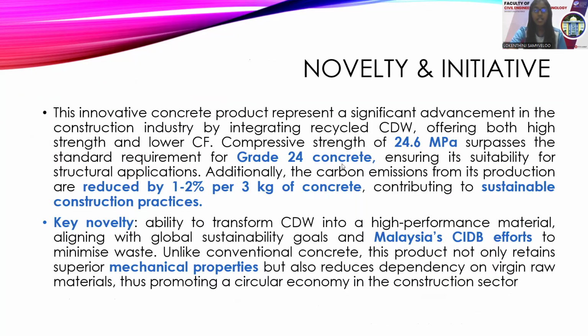Next, novelty and initiative. This innovative concrete product represents a significant advance in the construction industry by integrating recycled CDW, offering both high strength and lower carbon footprint. The compressive strength of 24.6 MPa surpasses the standard requirement for grade 24 concrete, ensuring its suitability for structural application. Additionally, the carbon emission from its production is reduced by 1 to 2% per 3 kg of concrete, contributing to sustainable construction practice.